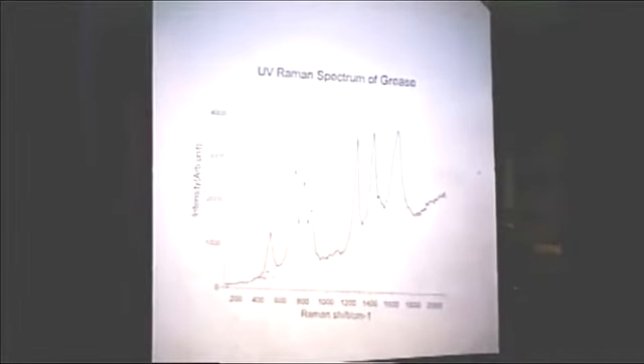We looked at a grease sample. Grease fluoresces tremendously. I mean, it's not like these samples don't fluoresce. As soon as you hit, for example, the grease sample with the UV beam, it fluoresces like mad. You can see tremendous amounts of light coming out of the sample, but it's all at the wavelength that doesn't bother us. Okay, there's just an example of a grease sample. So you get a nice, strong Raman. In fact, grease gives us one of the strongest Raman spectra that we've seen.